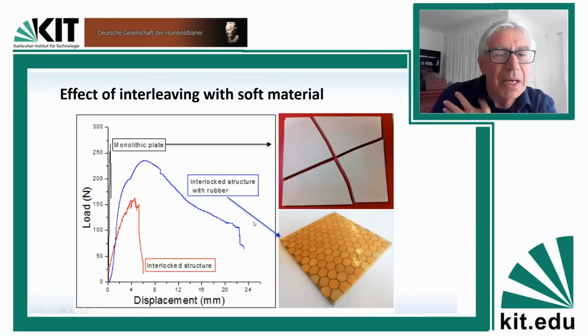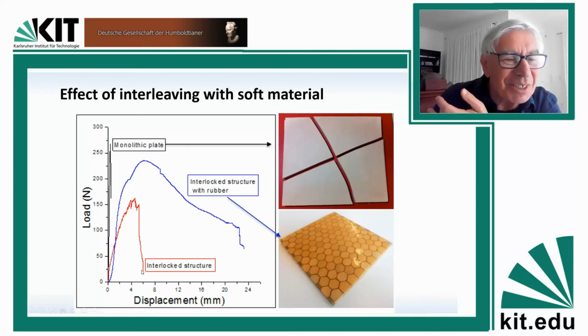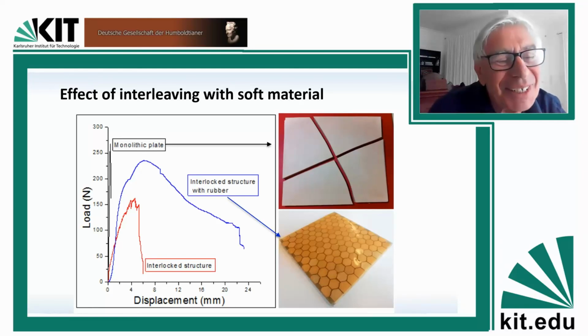If we look at the interlock structure, but without the resin, just our ceramic osteomorphic blocks assembled in this way, you have a response like that: a lower maximum load, yet some compliance, some ductility, some bendability of the structure. You get a pretty large plastic strain, or pseudo-plastic strain.